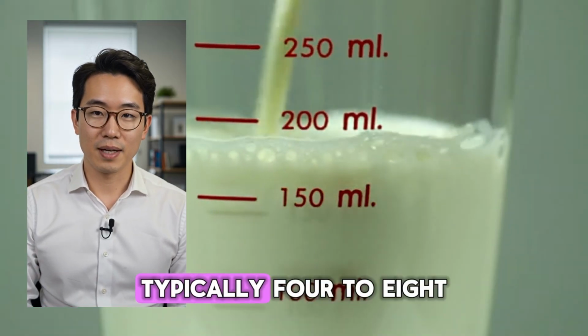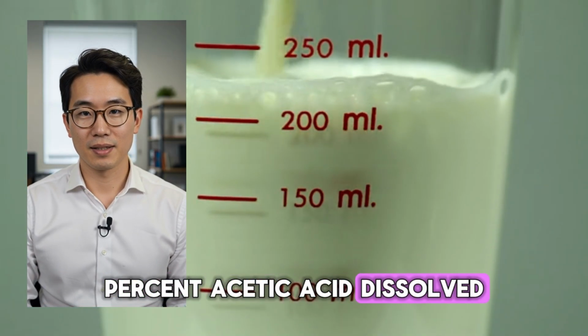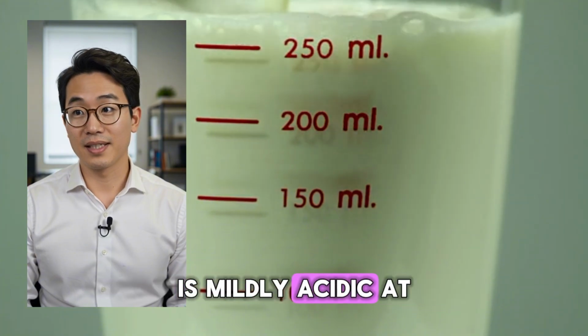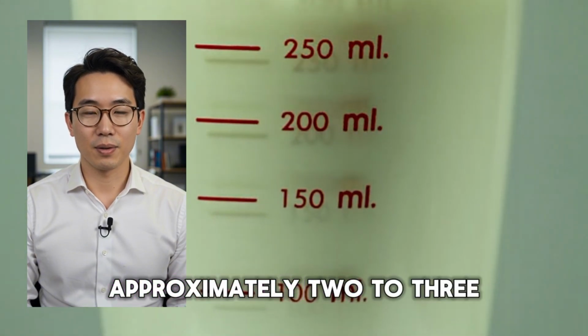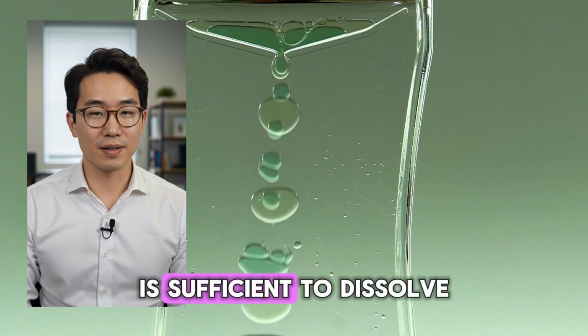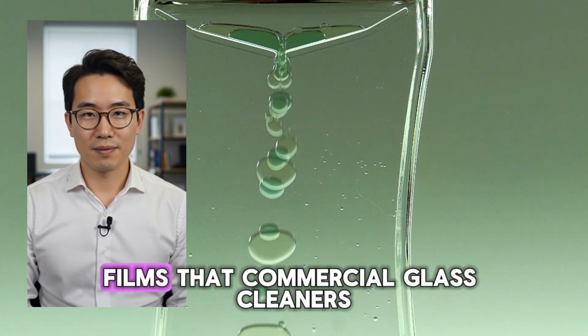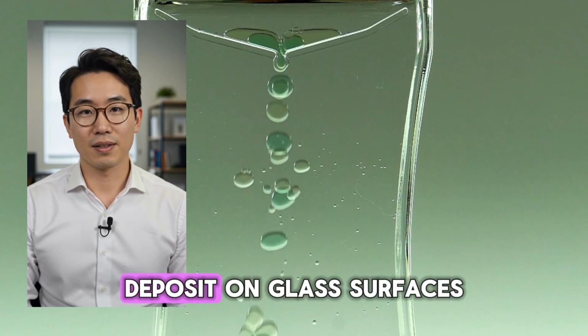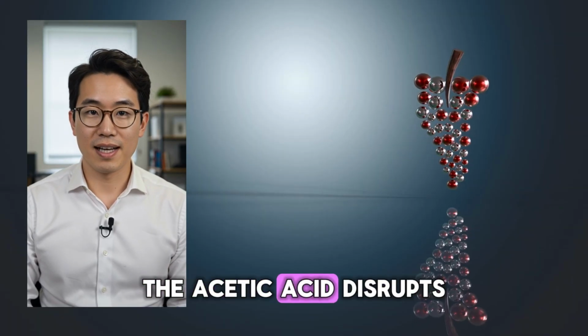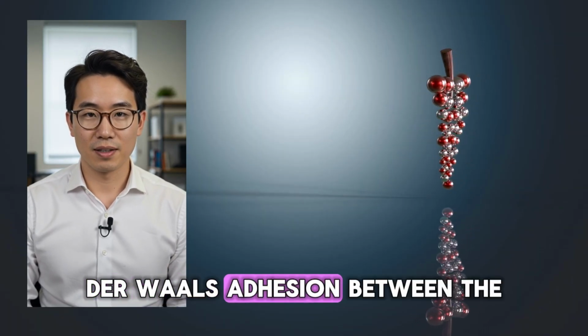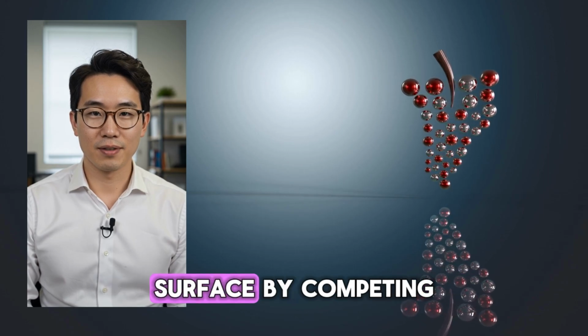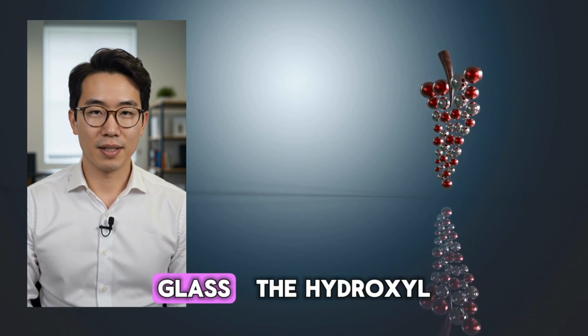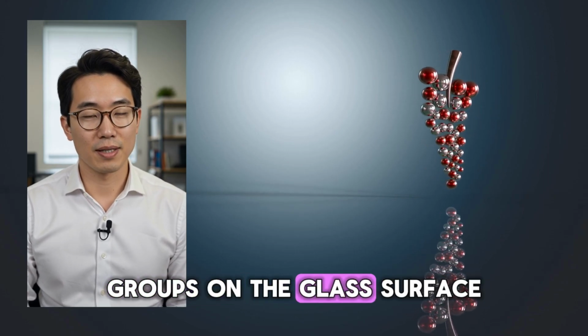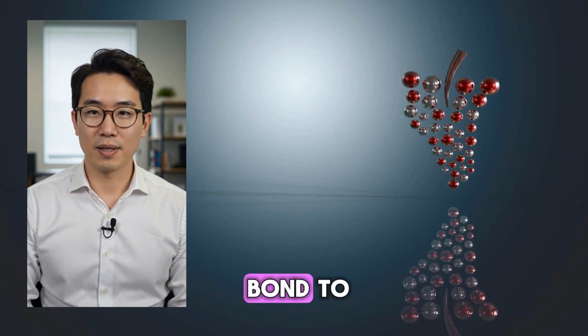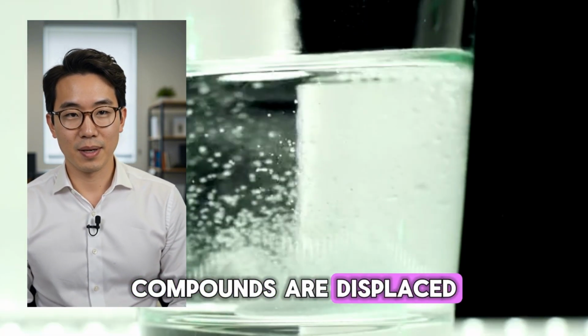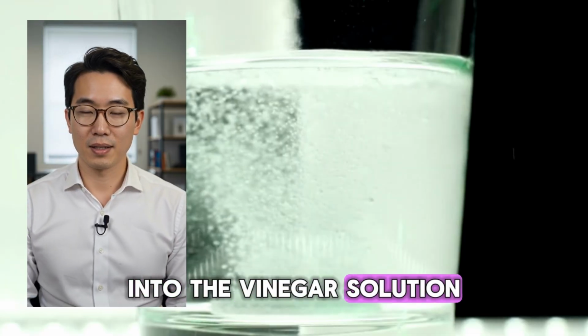White vinegar, typically 4 to 8% acetic acid dissolved in water, is mildly acidic at a pH of approximately 2 to 3. This acidity is sufficient to dissolve the polymer and surfactant films that commercial glass cleaners deposit on glass surfaces. The acetic acid disrupts the van der Waals adhesion between the polymer film and the glass surface by competing for the adhesion sites on the glass, the hydroxyl groups on the glass surface that the polymer compounds bond to. The polymer compounds are displaced from the glass surface and taken into the vinegar solution.